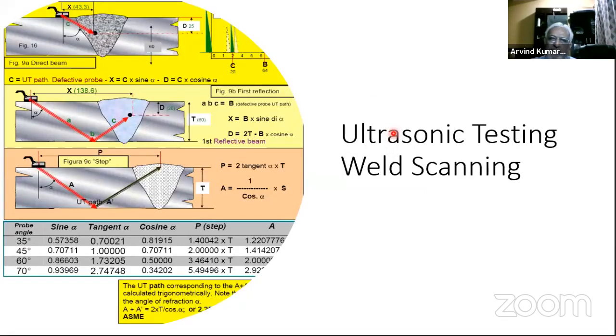So these are some of the scanning patterns. What we need to do is cover the entire weld. So we have to scan from half skip, where I get an indication from the root, to full skip, where I get an indication from the surface, and go a little beyond that to cover the reinforcement. I need to cover the reinforcement also.